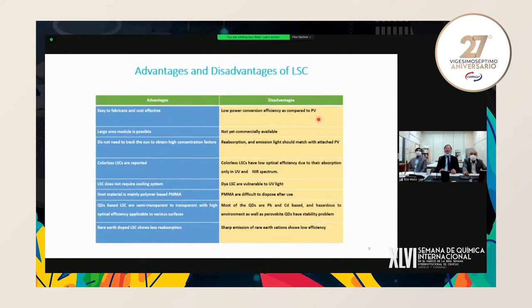Also, another issue is that we should match with the other PV. Colorless LSCs have a low optical efficiency due to absorption only in the UV and NIR, near IR spectrum. Dye LSCs, these organic dyes, are vulnerable to UV light, so may be degraded due to UV light. Also, PMMA is difficult to dispose of after use, but it's a long-term system. Most of the quantum dots are lead and cadmium. This is a very harmful and hazardous material. We should replace the lead or cadmium in the future.